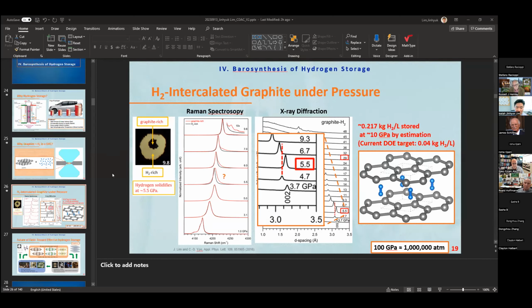Okay. Can you elaborate a little bit more? I didn't quite get your claim. So basically you have graphite and you are squeezing it with hydrogen. I don't know the hydrostatic limit of hydrogen, but you see a change in the diffraction when hydrogen crystallizes. So you're changing the condition. Probably you're no longer in hydrostatic condition, and you are crystallizing your pressure transmitting medium. So I don't know if the changes in the diffraction may be due to the external stress given by the crystallized hydrogen, or the loss of hydrostatic condition, and not from an intake of the hydrogen in the structure.